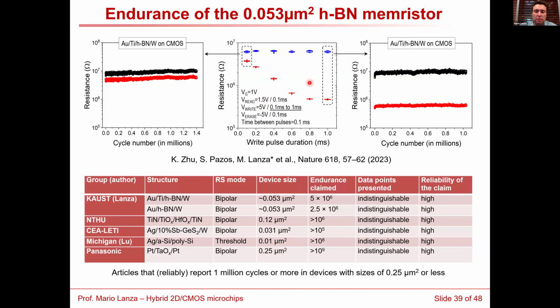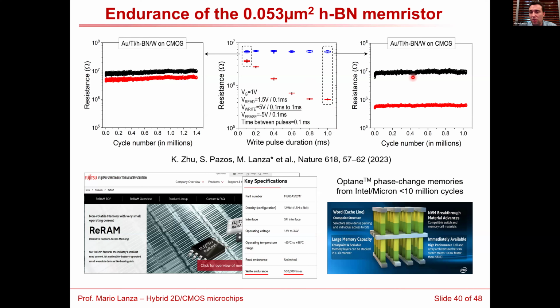So we were actually quite happy because these endurances and the size are similar to those in commercial devices. You see, these are ReRAM memories from Fujitsu made with metal oxides, and they promise 500,000 cycles, not more. And the phase change memories from Intel, well, the ones that they offered before, now they stopped the production, they offer 10 million cycles. So this is quite similar, and what we are doing now is to try to measure many more devices to make some statistics.